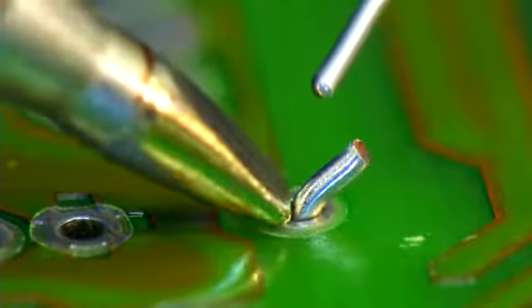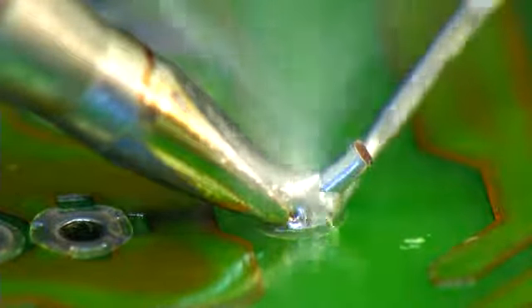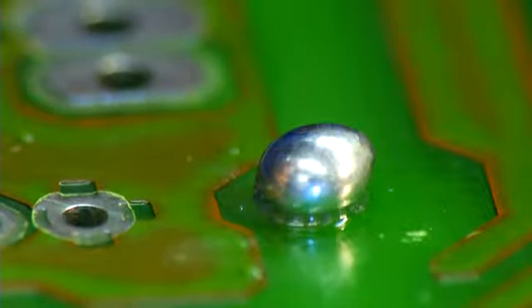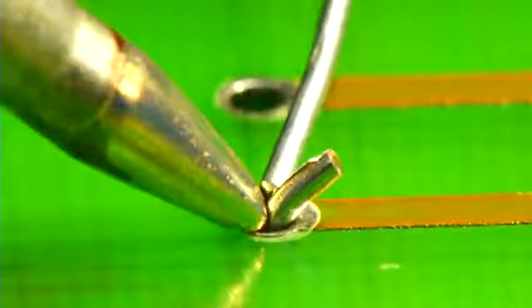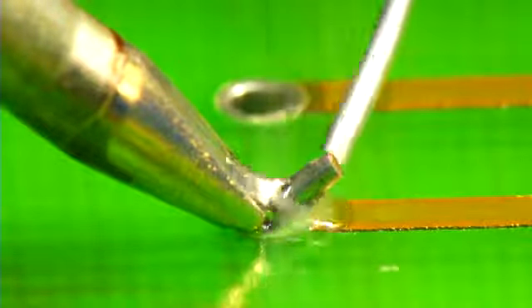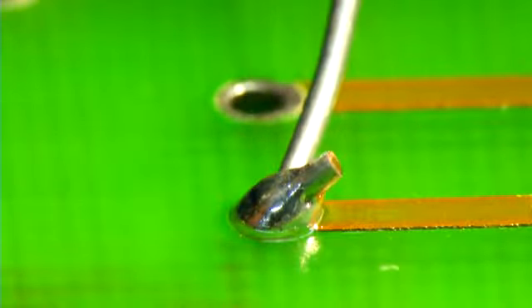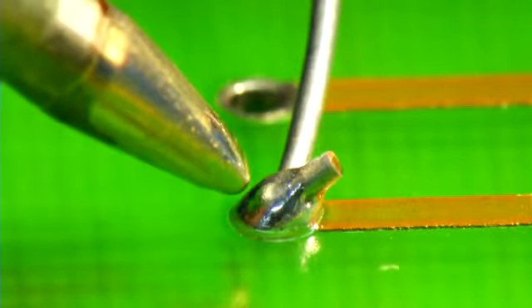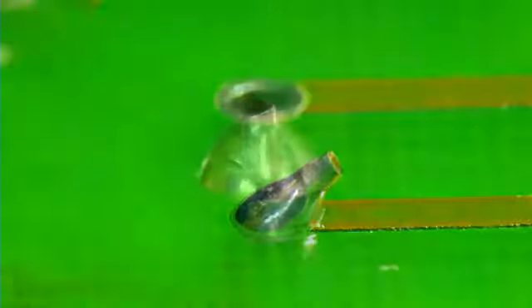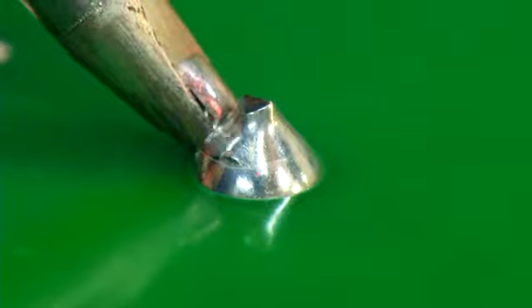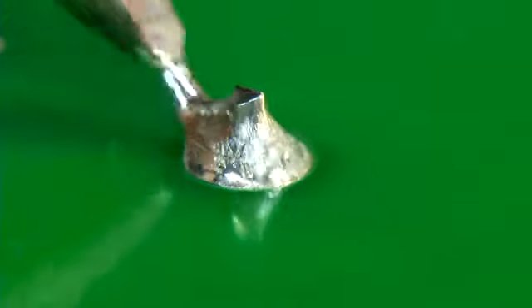Another problem is melting too much or too little solder into the connection. If you don't remove the solder wire at the right time, you could end up with something that looks like this. This time we removed the tip before the solder wire. Now we'll have to reheat the joint in order to remove the solder wire. Notice what happens when we reheat a tin lead solder joint? It doesn't look as smooth or as shiny as it was before.